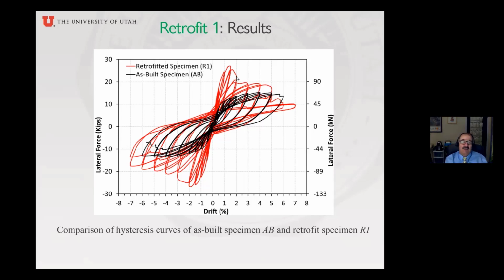So this was a little bit of a construction error on our part. The epoxy that was supposed to hold it in was not placed correctly. And so, as you will see, it pulled out, and in that case, it failed on one side of the wall. The other side of the wall, nothing failed. So it's really very good.